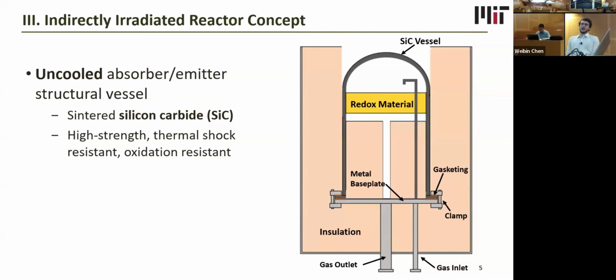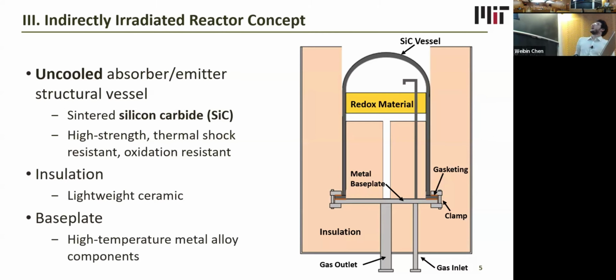So this is what our reactor concept currently looks like. This is not finalized, but this is what we're currently thinking. It features an uncooled absorber emitter structural vessel that is made entirely out of sintered silicon carbide. The reason we chose this material is because it is high strength, thermal shock resistant, and oxidation resistant. Around the entire reactor, we would have lightweight ceramic insulation to prevent heat losses, and we would also have this insulation separating the hot redox zone from the cooler zone down here, which would be serviced by high temperature metal alloy components, which cannot withstand the full temperatures of the redox phase.